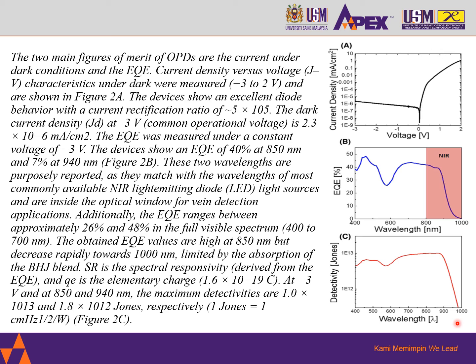The obtained external quantum efficiency values are high at 850 nanometer but decrease rapidly towards 1000 nanometer, limited by the absorption of the BHJ blend. SR is the spectral responsivity derived from the EQE, and q is the elementary charge, 1.6 x 10^-19 coulomb. At -3 volt and 850 and 940 nanometer, the maximum detectivities are 1 x 10^13 and 1.8 x 10^12 Jones respectively. 1 Jones is equal to 1 centimeter hertz^1/2 per watt, as shown in figure 2c.